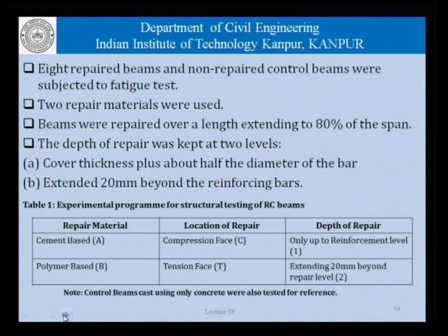We used 2 repair materials and the beams were repaired over a length of 80% of the span. The depth of repair was kept at 2 levels, the cover thickness plus about half the diameter of the bar, and in another case the repair thickness extended 20 millimeters beyond the reinforcing bars. Now, this is similar to the kind of discussion that we had earlier about a good repair and a bad repair system. In one case, if this is the bar, the repair material was cast up to this point, which is the cover depth plus half the diameter of the bar. In another case, the repair material extended all the way beyond to the extent of 20 millimeters behind the bars. And as we said, there were 2 repair materials used, one was cement based and the other was polymer based.